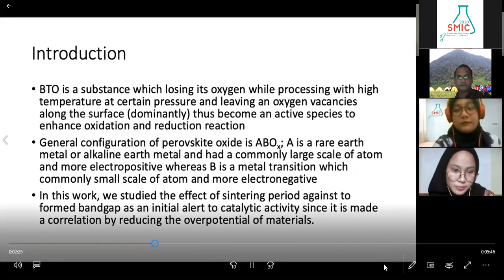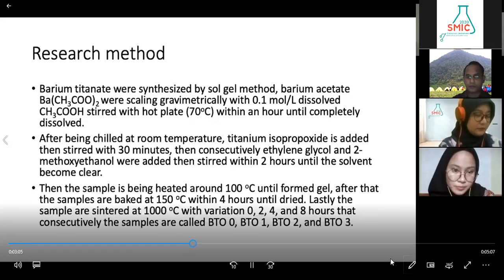Then for perovskite oxide in general, the general configuration is ABOx. A is a rare earth metal or alkaline earth metal, commonly with a large atom and more electropositive than B, because B is a transition metal, commonly with a small atom and more electronegative. In this work, we studied the effect of sintering period on the band gap formed, as an initial alert to catalytic activity, since it is correlated with reducing the overpotential. Basically, we use barium acetate and titanium isopropoxide, which were stirred and heated at 1000 degrees with variation of sintering period.